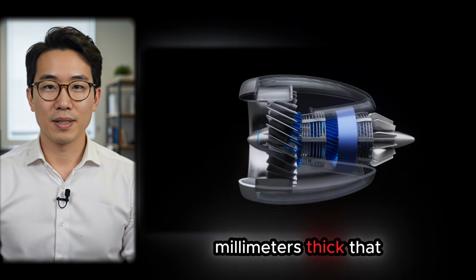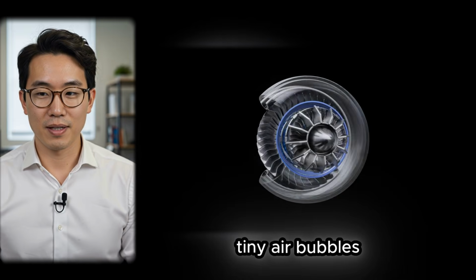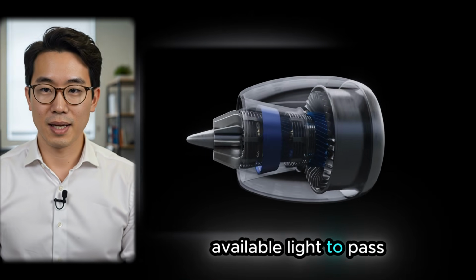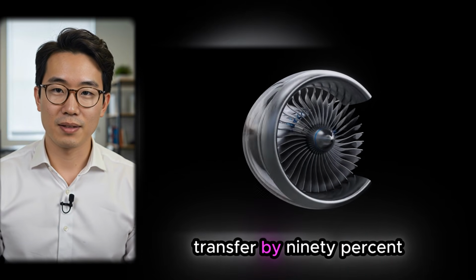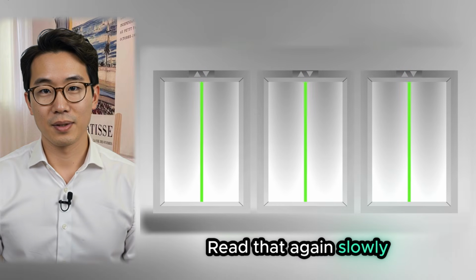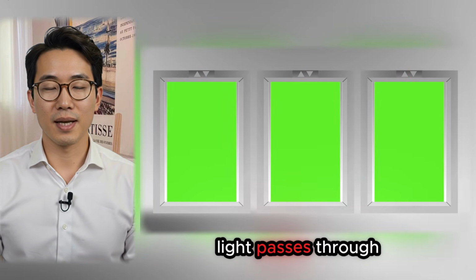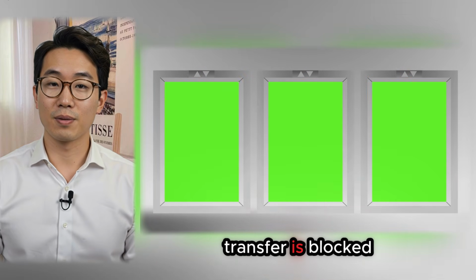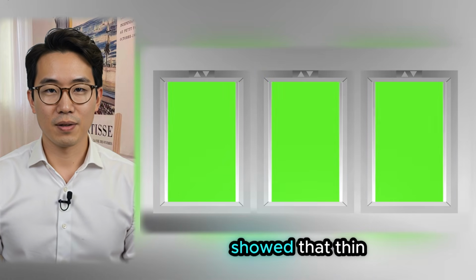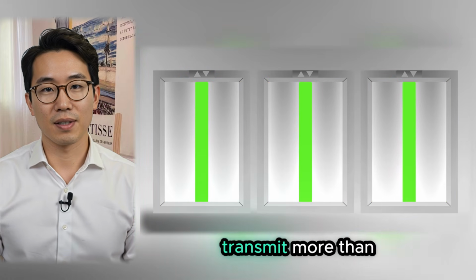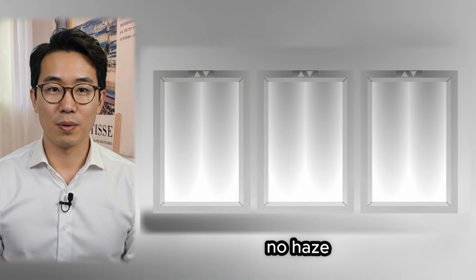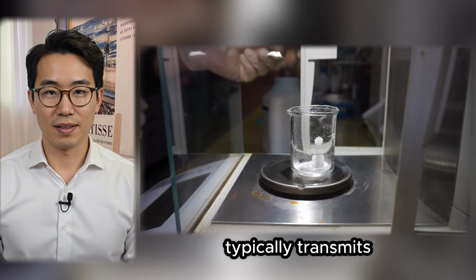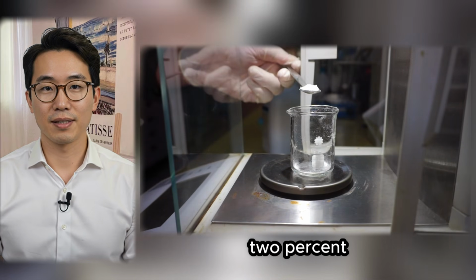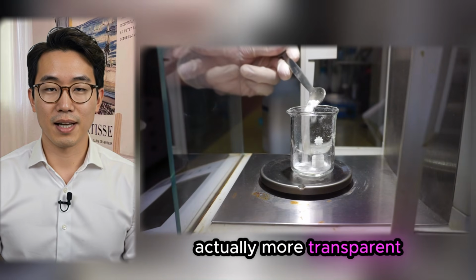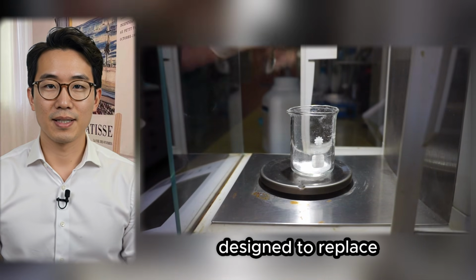Researchers at the University of Colorado Boulder created a coating just 5 millimeters thick that contains millions of tiny air bubbles, and it allows 99% of the available light to pass through while reducing heat transfer by 90%. Read that again slowly. 99% of visible light passes through, while 90% of heat transfer is blocked. Consider that tests showed that thin Mochi sheets transmit more than 99% of visible light with almost no haze, while ordinary window glass typically transmits less than 92%, meaning this insulating material is actually more transparent than the plain glass it is designed to replace.